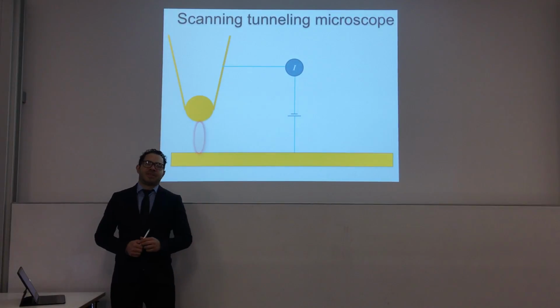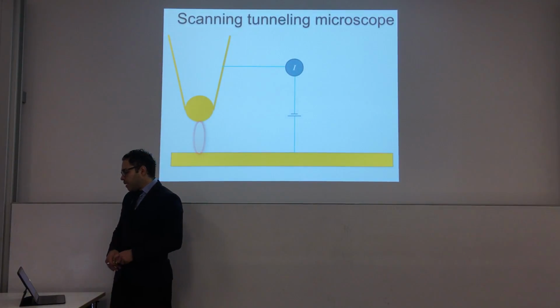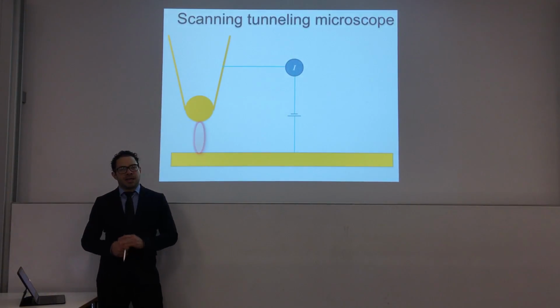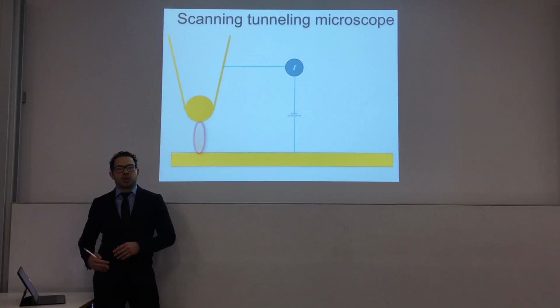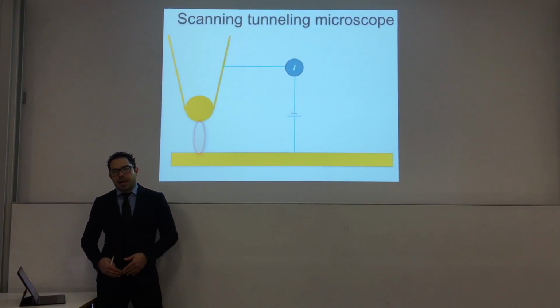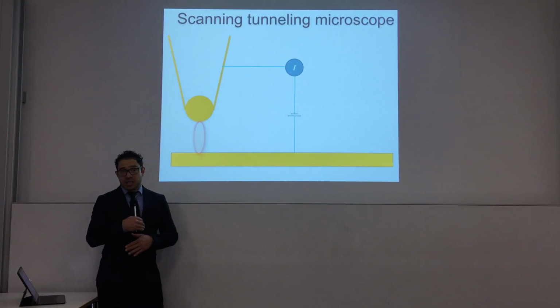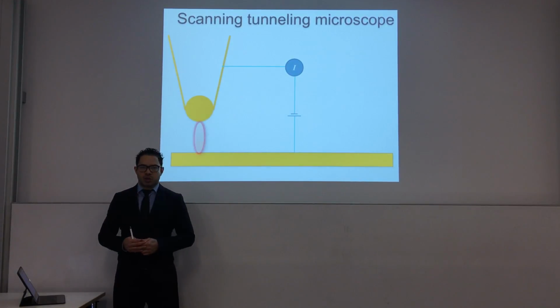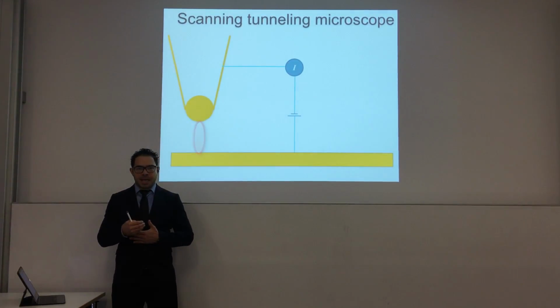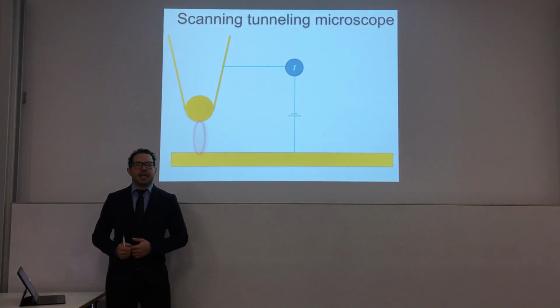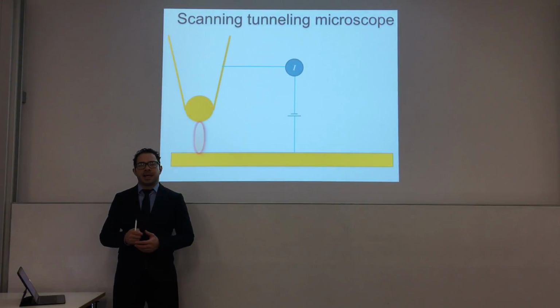The particular example of STM is very illustrative. What happens here is that you need a metallic tip and you need a metallic substrate. If you apply a potential difference between these two, and of course if they are not touching, classically you will not expect to measure any current since they are not in mechanical contact. But quantum mechanically, there is a non-zero probability that electrons will flow from the tip to the sample.